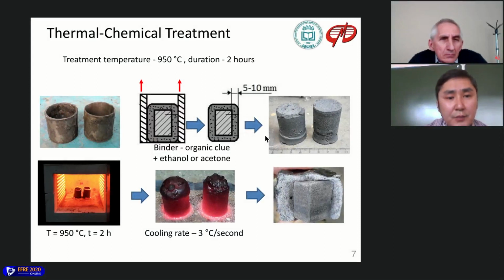And thermochemical treatment as a first step of combined treatment was done in the following order. So where treatment paste and sample were placed in cylindrical molds. After drying, molds were removed and obtained briquettes were dried for about an hour. After that, they were placed in a muffle furnace preheated to a treatment temperature of 950 degrees Celsius for 2 hours. After treatment, samples were cooled down at ambient temperature,